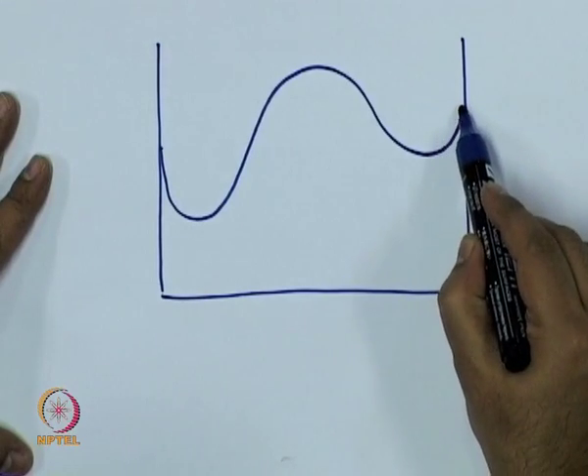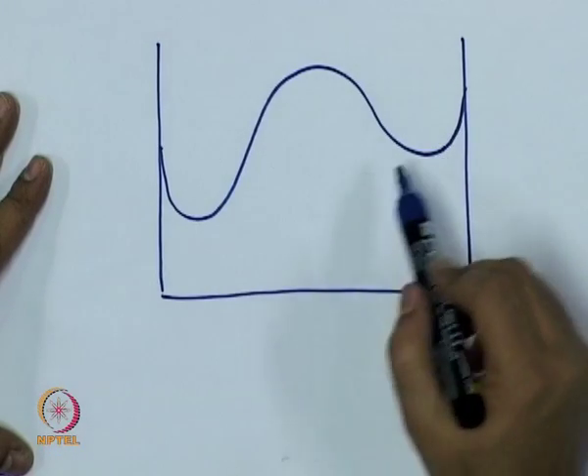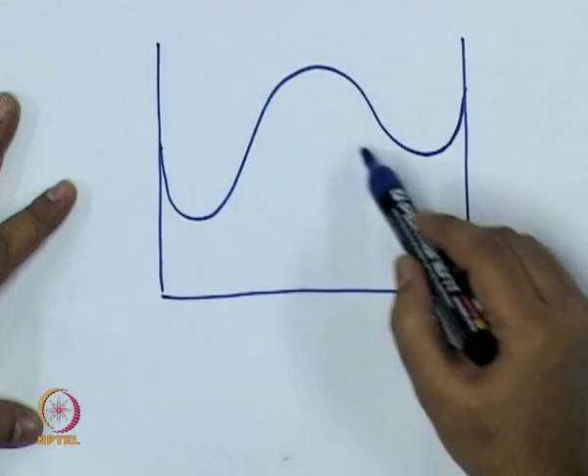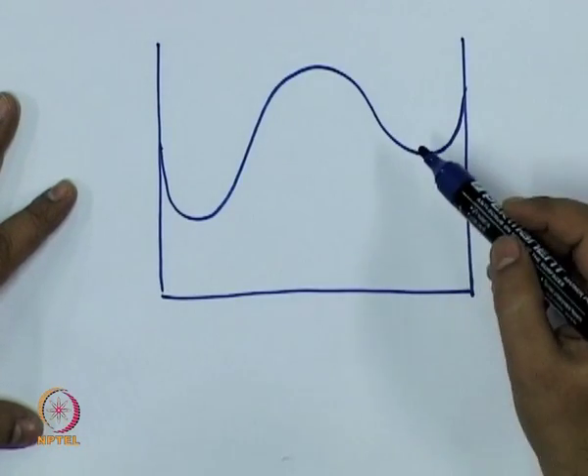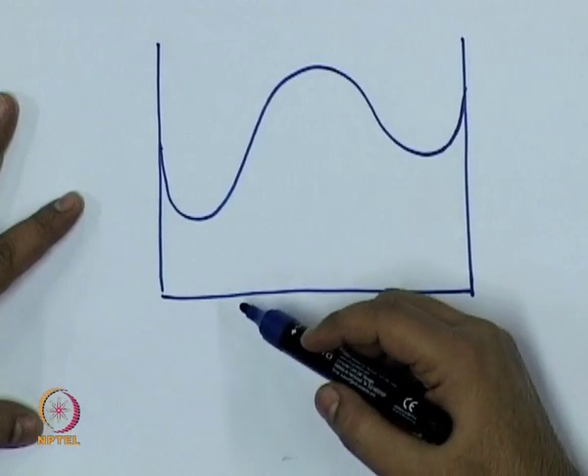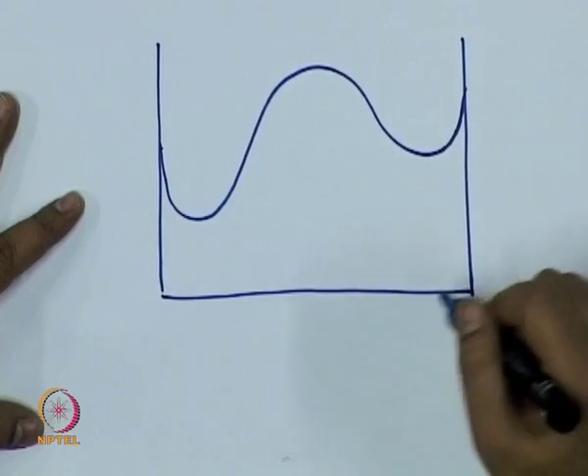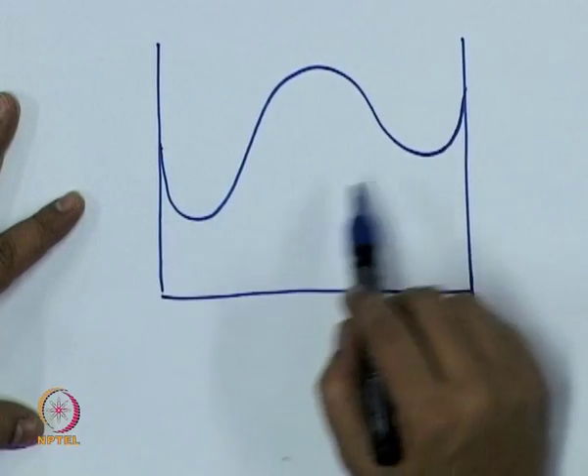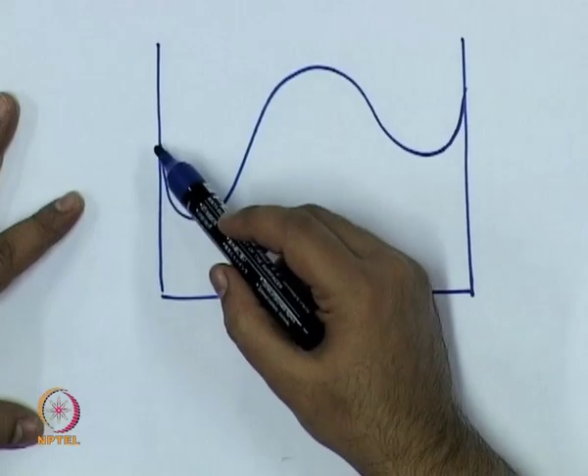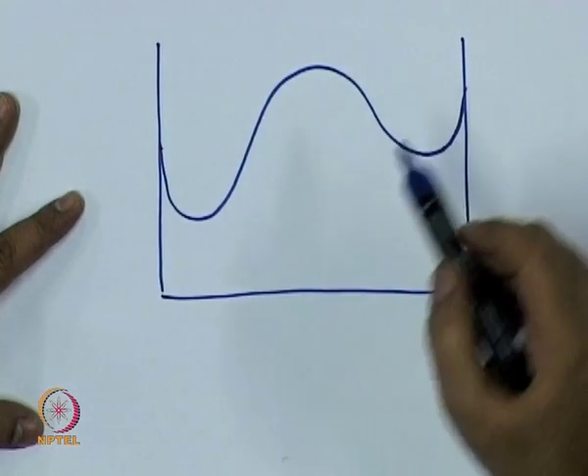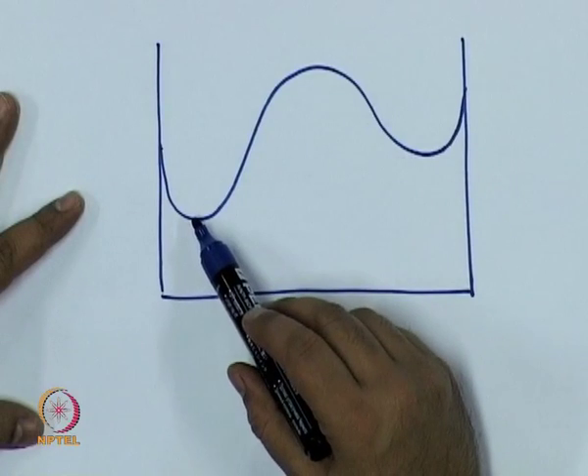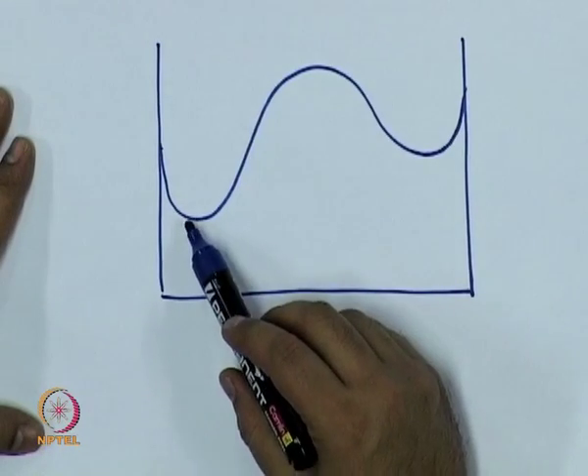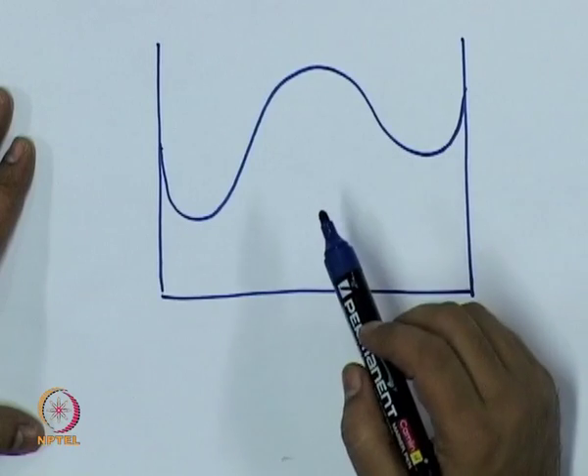There is a concave region with two wells and one maxima. If you just look at the free energy of mixing, the models we had were symmetric with minima at the same level, but when you add the end composition free energies G_A for pure A and G_B for pure B, that is like a straight line, so it shifts and the two minima need not be at the same level. Because we have drawn a continuous curve for the two end phases, it means the crystal structures for these two phases are basically the same.